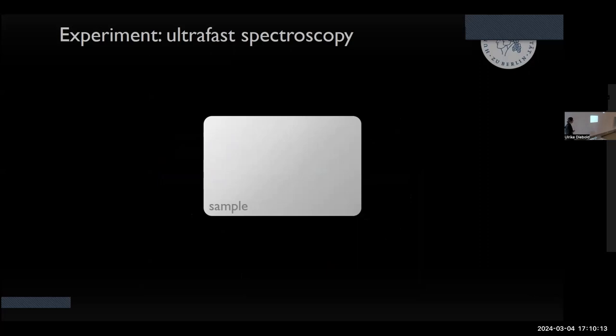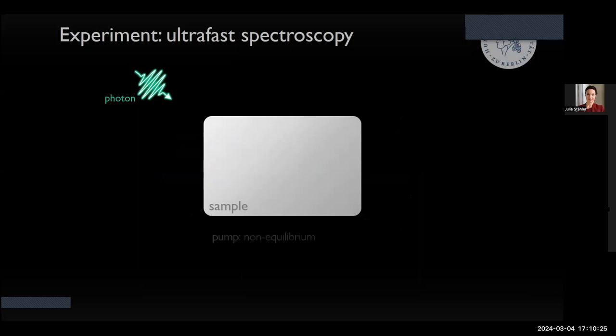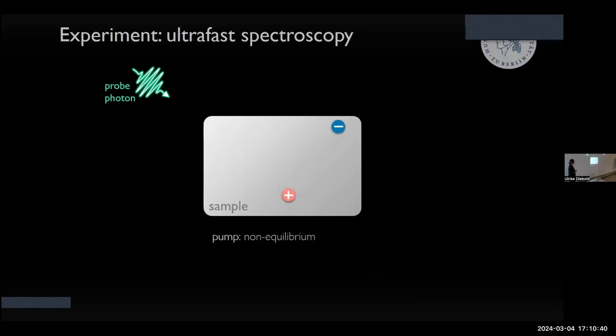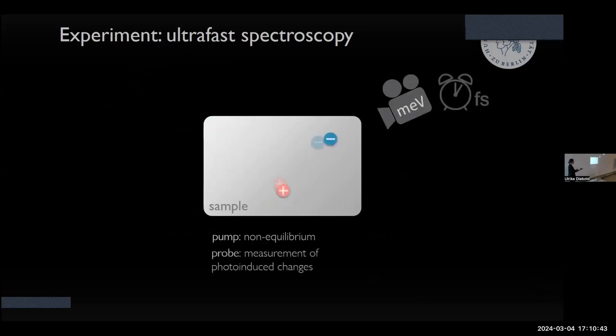This means we want to look at what happens in a material after absorption of light on femtosecond or picosecond timescales. In order to do that, we use a pump probe approach. We use a first laser pulse. It excites the system, brings it into non-equilibrium conditions. And then we use a second, time-delayed laser pulse. By changing the time delay, we can then monitor the material properties as time proceeds, because the second pulse does the spectroscopy step. Today, I will only show you photoelectron spectroscopy results, but of course, you can also do this with nonlinear spectroscopies, optical spectroscopies, etc.